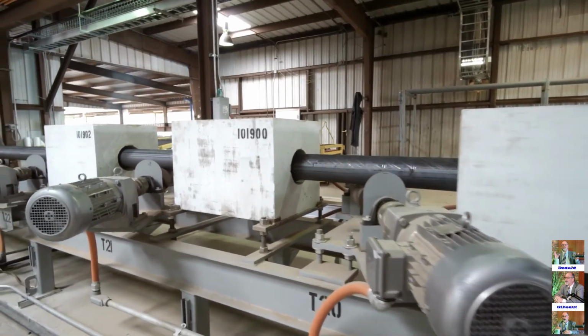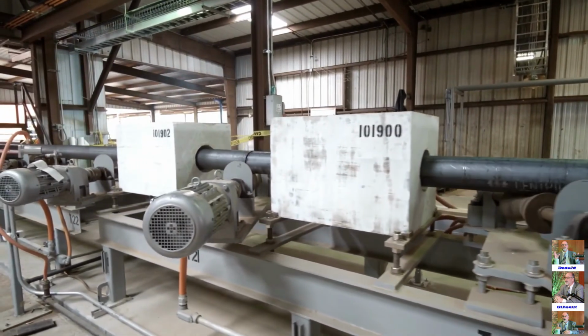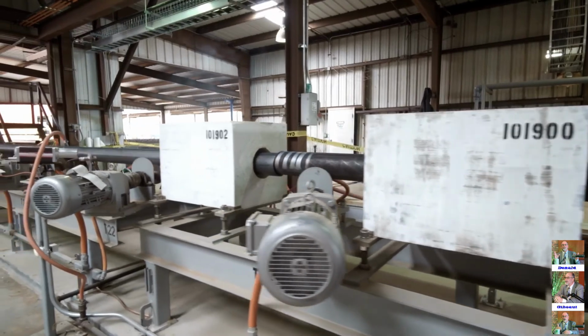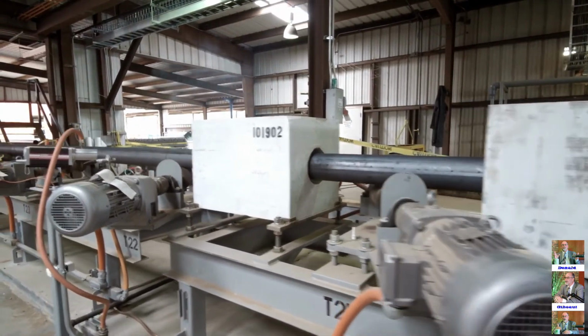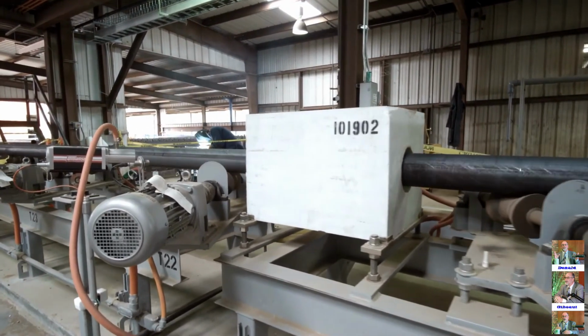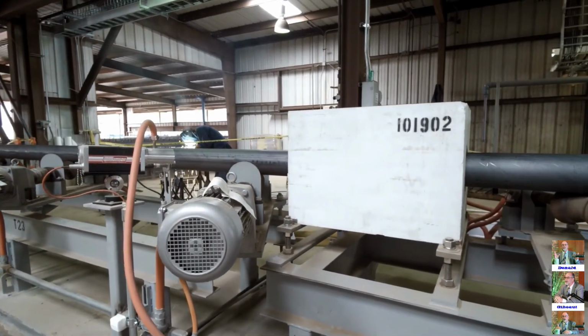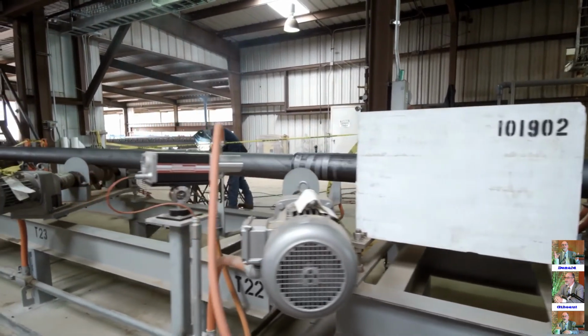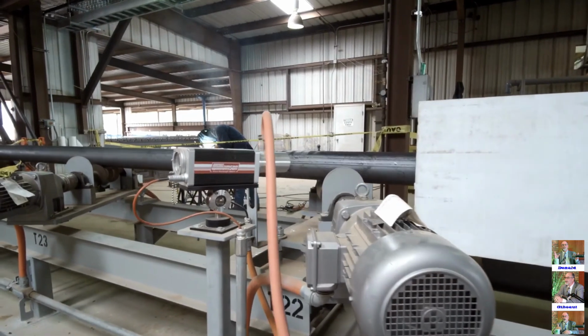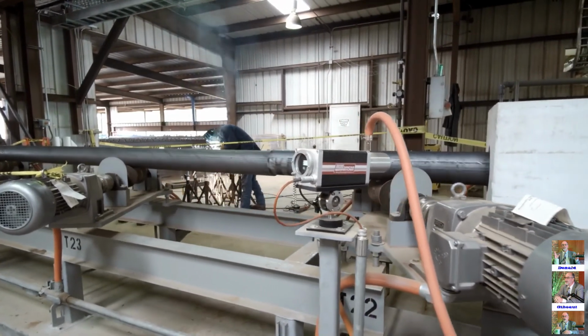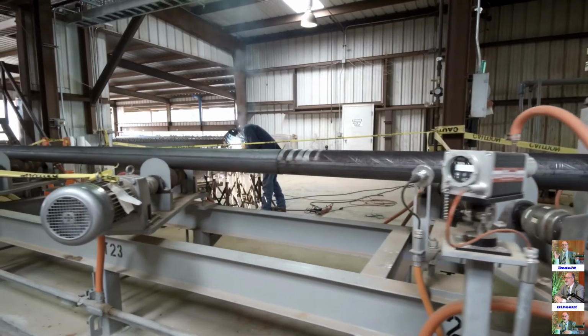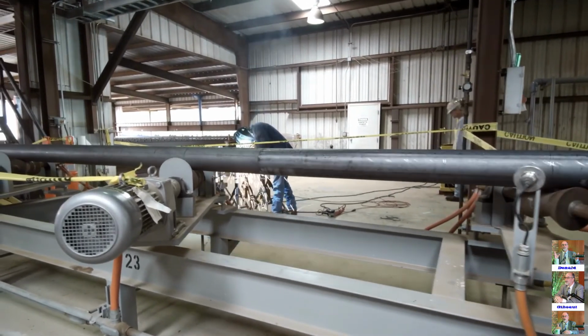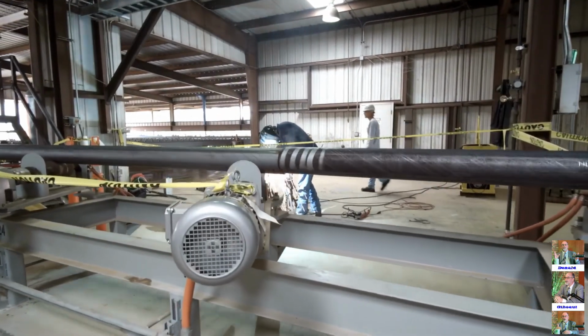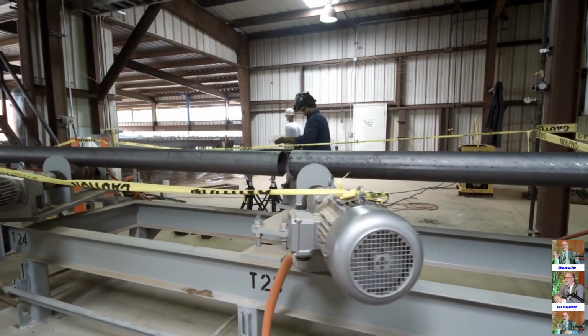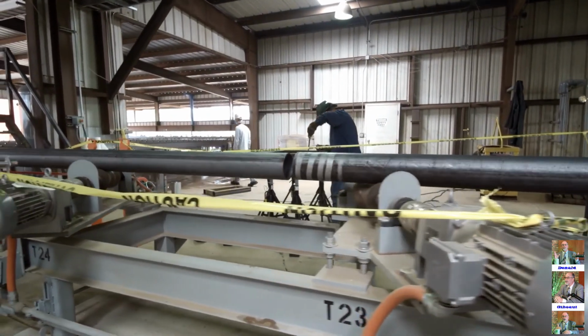It's progressively heated. The temper typically gets anywhere from 900 and some degrees to 1350, depending on the alloy. And here's the final temperature infrared monitor to feed back to the controls. Not so much of a scale issue here because we're below that scale point of 1400 degrees. So it's more of a 1-to-1 here in the temper, but now you can see it start to separate.